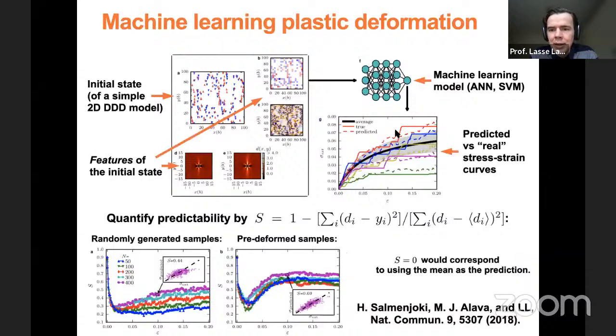So here are basically the predicted stress-strain curves, which are the dashed lines, and the real ones are the solid lines. You can see that the model is not really able to resolve the individual events. Let's say here we have one strain increment, then you have a stress increment, another strain avalanche. But the dashed line kind of follows the overall curve, but it doesn't resolve the individual events. And this is one way of seeing that these individual events are actually hard to predict.